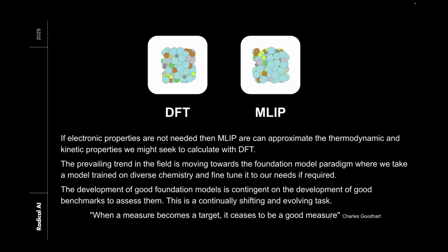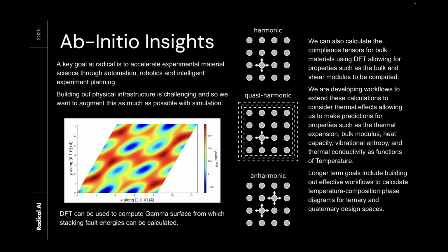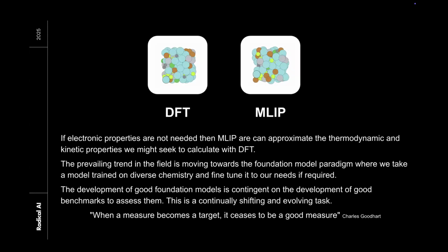So this is actually a real-time graphic of the speed of DFT against the MLIP. DFT is about 1,000 times slower, which is critical because these quasi-harmonic and anharmonic approximations require thousands of times more evaluations than the harmonic approximations.